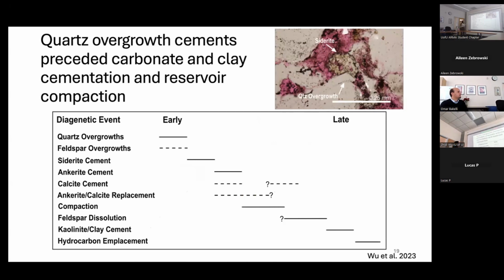And this one is the categorization of those 5 rock phases. They all share a similar, not the same, but similar diagenesis sequence. In all of them we see quartz overgrowth, which is a non-reactive component of the rock, formed very early in the history, like they formed first. And then other overgrowth precipitates, and then siderite cement starts, and there's some replacement, compaction, the overpressure environment, and some compaction of the formation. Then there's some dissolution, clay cement precipitation, and finally hydrocarbon emplacement, where the oil forms, filling those pores.